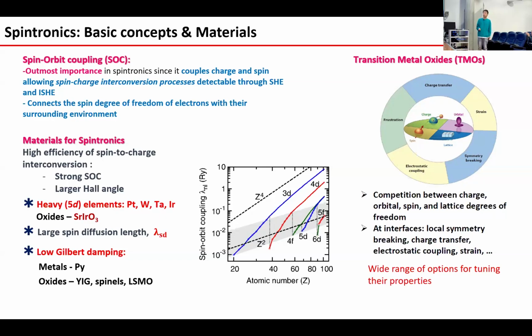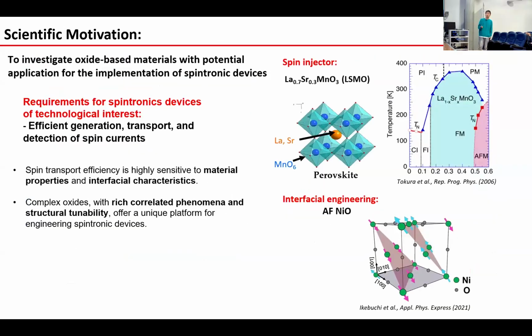Because it has a competition between the charge, orbital and lattice degrees of freedom, and it also has a high tunability of the electronic structures at the interfaces, for example, local symmetry breaking, charge transfer, and so on. So it provides a wide range of options for tuning their properties. So our scientific motivation is to investigate oxide-based materials with potential application for the implementation of spintronic devices.